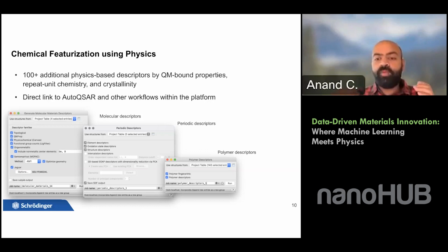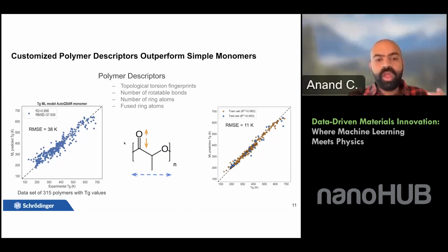And finally, for example, for polymer materials, we have a specific panel that can generate polymer fingerprints and polymer descriptors. To go into more detail about these, this slide demonstrates how we can improve the accuracy of models by taking into account specific descriptors that have been tailor-made for polymers. For example, we loaded around 315 polymers from the Polymer Handbook with glass transition temperature values. If we load these data sets into AutoQSAR and train a machine learning model, we get a root mean square error of around 38 Kelvin for the prediction of the glass transition temperature.